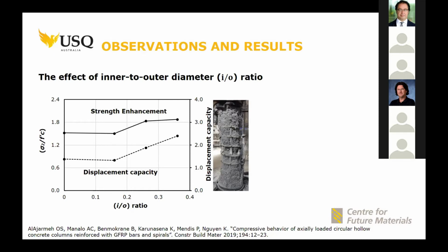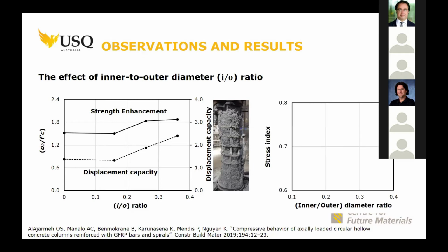We studied and investigated it in depth to describe that phenomenon by using something called a stress index of the reinforcement and the core. From that analysis, we found that if the stress index inside the concrete is more than the stress index of the lateral reinforcement, then the failure will be in the core, not in the spiral. Because of that, we selected 0.36 as an optimal inner to outer diameter ratio to be used afterwards in the other samples.